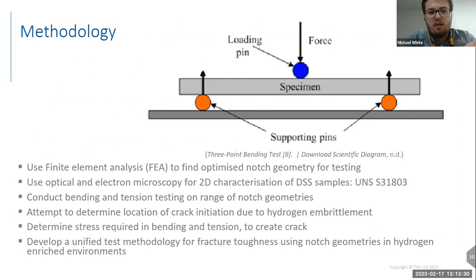During our testing, an FEA model will be utilized to find an optimized notch geometry for testing, as changing the notch's width and depth will alter the effect it has on the stress concentration at the notch tip. A notch which is too wide or too narrow will not provide the correct stress concentration to assess the crack formation. The wider a notch is, the lower the stress concentration at the notch tip.